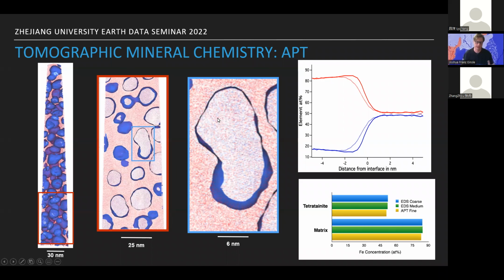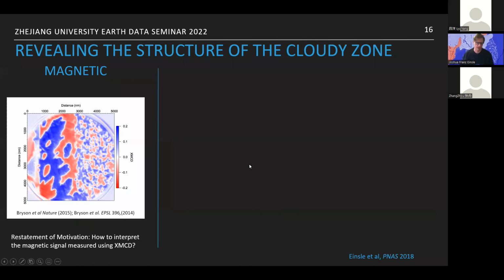And this is all without using any standards, because really at the nanoscale there aren't standards that exist, and that is a big point of discussion that we could have at some other time. But the point being that we have two methods that ran completely independently, and we arrived at the same answer within about 1%, which was a very good result. So the upshot of this now brings us to the second complication, which is that we're still trying to interpret this.